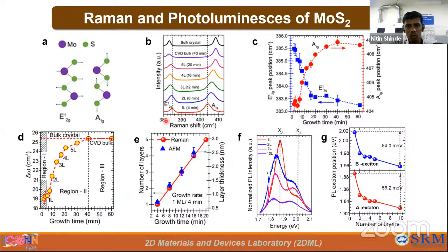We can see here we started growth from 1 minute, up to 60 minutes. As we increase the growth time, both E2G and A1G shift in opposite directions, meaning that increasing the growth time increases the number of layers, which means increased thickness of the sample. We can see here the exact positions of E2G and A1G. We can see that E2G varies rapidly below 20 minutes compared to A1G. We take advantage of A1G and E2G to identify the number of layers of MoS2.